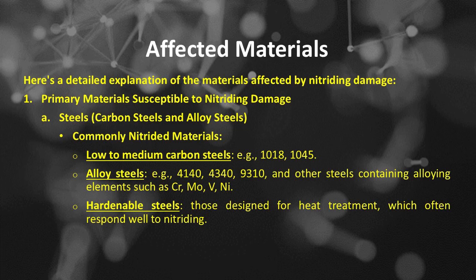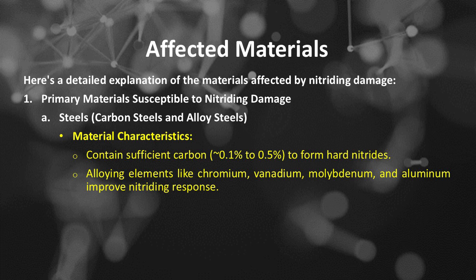Number 1 is primary materials susceptible to nitriding damage, which includes: A, steels, carbon steels and alloy steels. Commonly nitrided materials include low to medium carbon steels, such as 1018 and 1045; alloy steels, such as 4140, 4340, and 9310, and other steels containing alloying elements such as Cr, Mo, V, Ni; and hardenable steels, those designed for heat treatment, which often respond well to nitriding. Material characteristics include sufficient carbon, up to 0.1% to 0.5%, required to form hard nitrides, and alloying elements like chromium, vanadium, molybdenum, and aluminum that improve nitriding response.